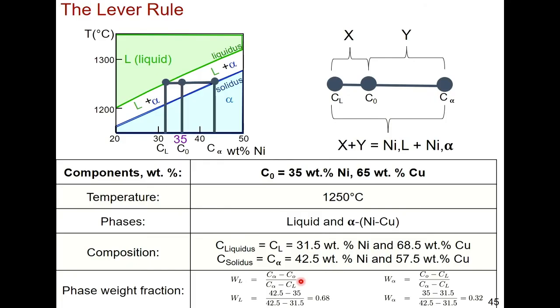Okay, so what I just did was what's called the lever rule. So if you're given a C naught, if you're given a composition of the system, in this case, how much weight percent of nickel do you have in the system, you can calculate, if given the temperature, what is the Cl, as well as what is the C alpha. In this case, it's the solid, where it touches the solidus line. And you can figure out the phase weight fraction.